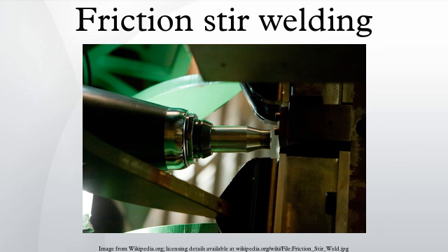Insufficient weld temperatures, due to low rotational speeds or high traverse speeds, for example, mean that the weld material is unable to accommodate the extensive deformation during welding. This may result in long, tunnel-like defects running along the weld, which may occur on the surface or subsurface. Low temperatures may also limit the forging action of the tool and so reduce the continuity of the bond between the material from each side of the weld. The light contact between the material has given rise to the name kissing bond.